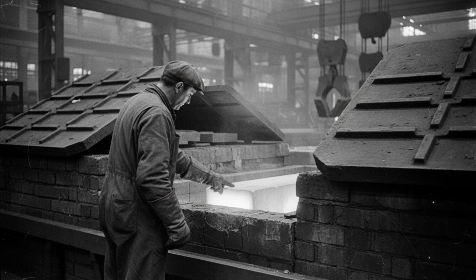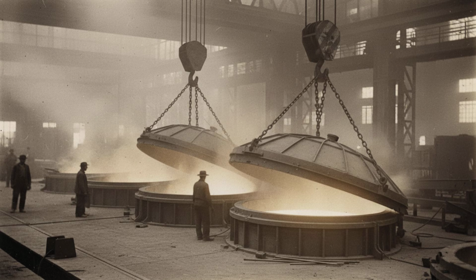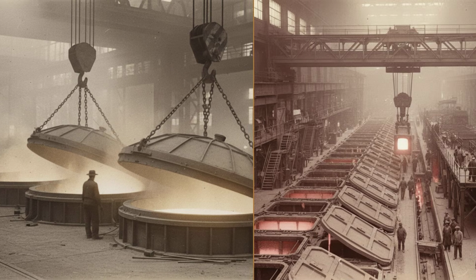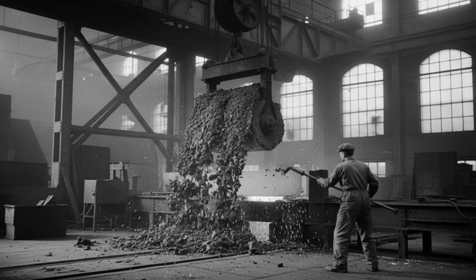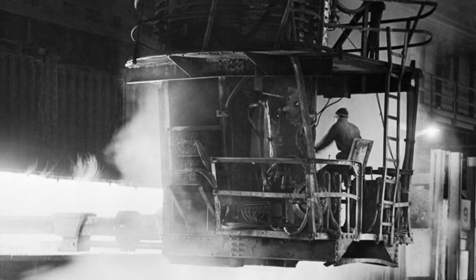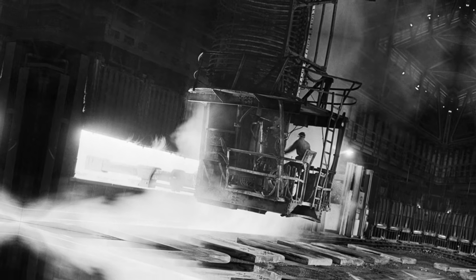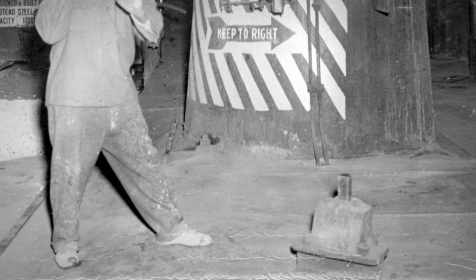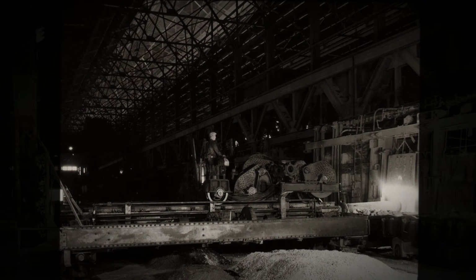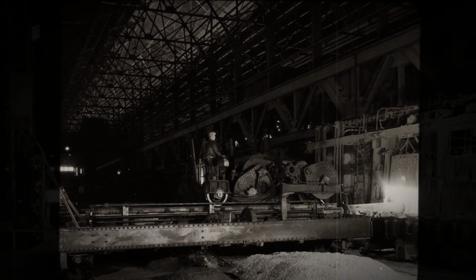The reducing atmosphere served a metallurgical purpose. It prevented surface oxidation of the ingot steel during the soak period, which would have produced a scale layer the rolling mill rolls would then have to work through. But that atmosphere was also a fuel-rich environment at 2,200 degrees Fahrenheit that could not be entered, could not be inspected during operation, and contained no margin for anything that went wrong inside it.